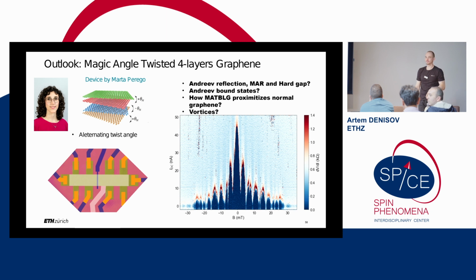And how does the band structure look? There is a dispersive band, a gap, just one flat band, and then a dispersive band. And the two layers in the middle, the twist angle is not necessarily the magic angle to get superconductivity? No, all the angles should be right. You have three twisted angles.